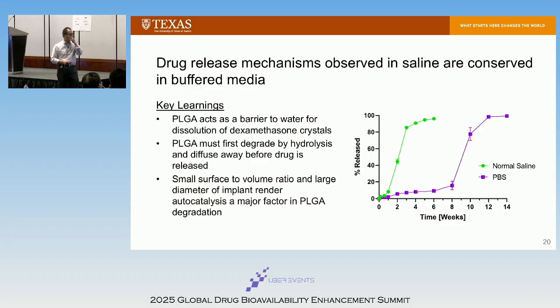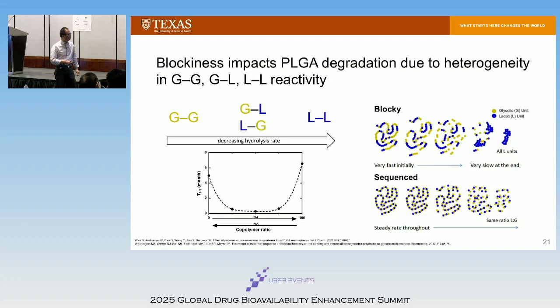Okay, so I was telling you earlier, if I run this dissolution in phosphate buffer, it's a 3 months dissolution testing, right? Because now you get this even more dramatic protective effect by the dissolution media. So going back, while we're doing this study, we're really trying to understand how does PLGA blockiness affect this, right? So with Nate's group, they are looking at those reaction kinetics, and